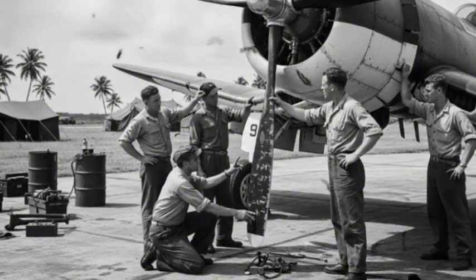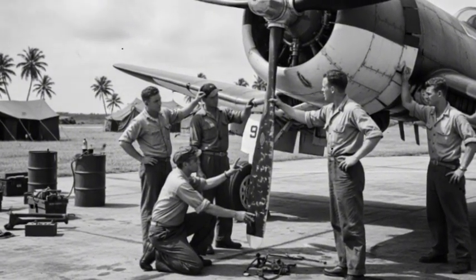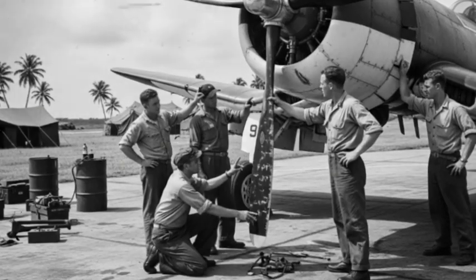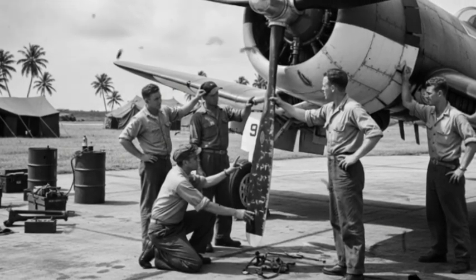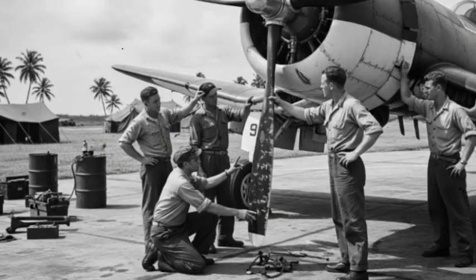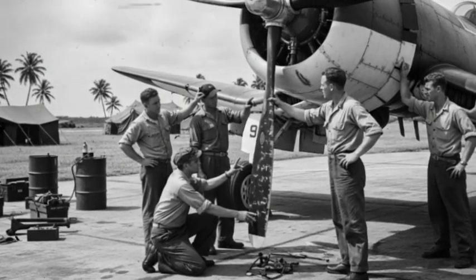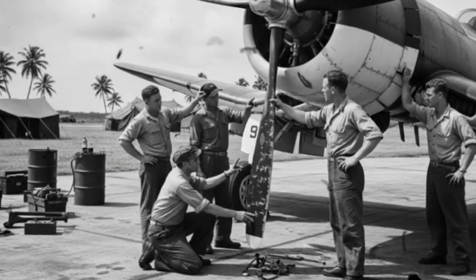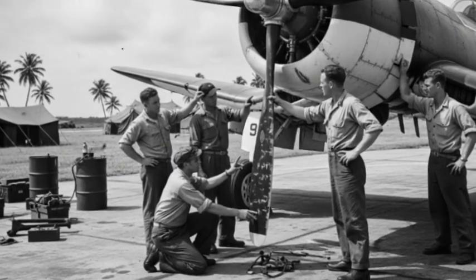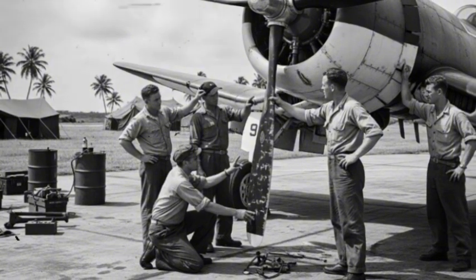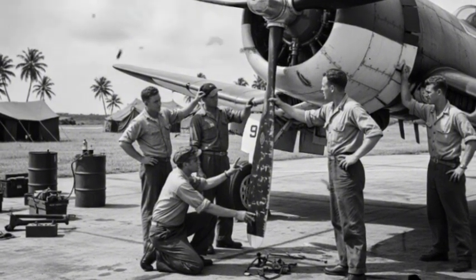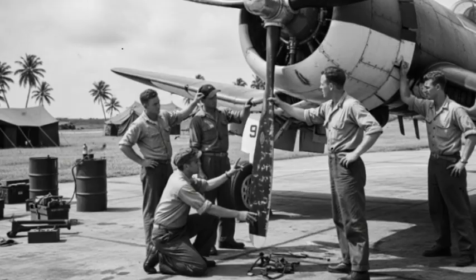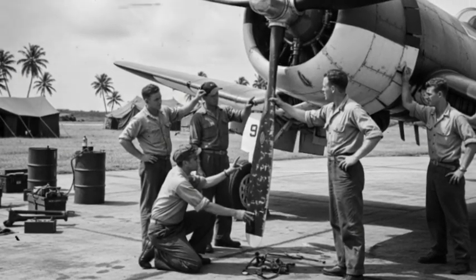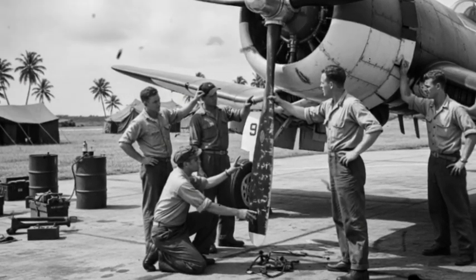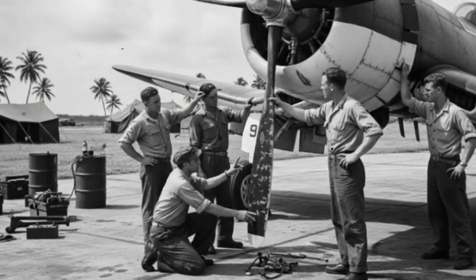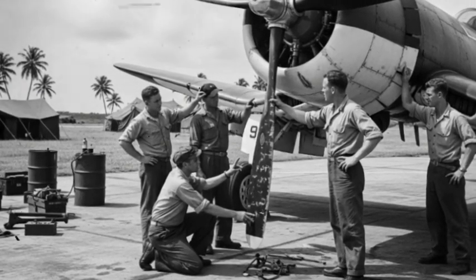Through the first 4 months of 1943, the Marine Corps squadrons flying Corsairs in the South Pacific reported 17 propeller failures resulting in aircraft loss or serious damage. 3 pilots died when propeller disintegration led to engine failure over water. The standard 24ST alloy was performing exactly as designed. It was failing in predictable ways when stressed beyond specifications. The problem was that combat conditions routinely exceeded those specifications. The Corsair needed a propeller that could survive the impossible, not one that failed predictably when confronted with it.